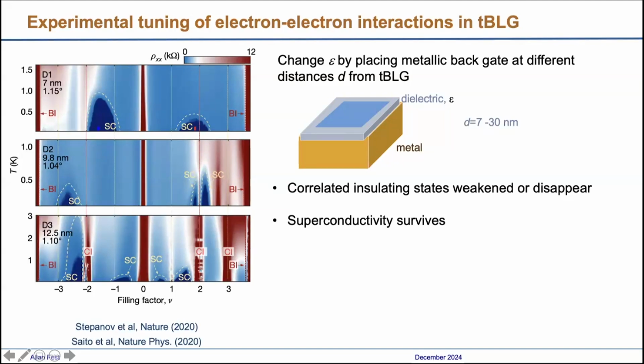For example, there are two papers from Dima Efetov's group and also Andrea's group, where they place a metallic gate very close to the twisted bilayer graphene. The distance is between 7 and 30 nanometers. What they see is that the correlated insulating state weakens or disappears. For example, here this is weakened, but superconductivity survives.